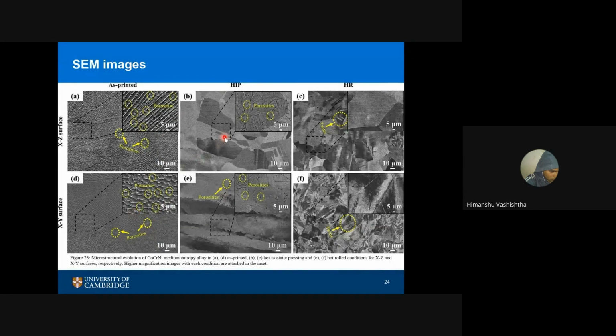When you apply hot isostatic pressure, what does this mean? The temperature was high while we applied pressure from all sides, that's why it's called isostatic pressure, at high temperature. What it did: the heat changed the crystallography, and it also minimized the porosities.